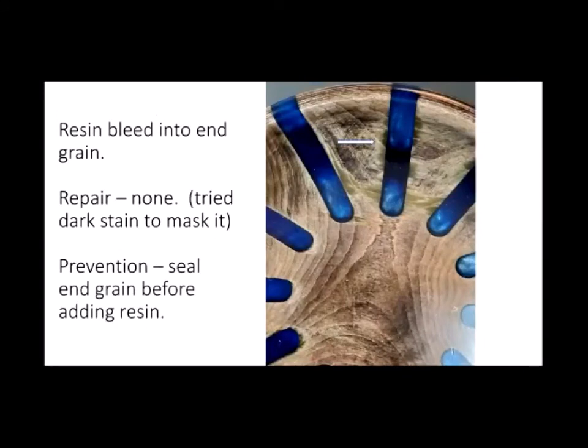Here's another problem on a bowl that I was doing when I was doing some of my router work. Right up in here, you see this arrow, when I poured, I cut these grooves, and on the parts where this was end grain on the inside of these grooves, the resin bled into the parent wood. And you can see it here and on this side here. And this is actually maple. It wasn't this dark. And so I attempted to stain the wood darker in order to try to mask that.